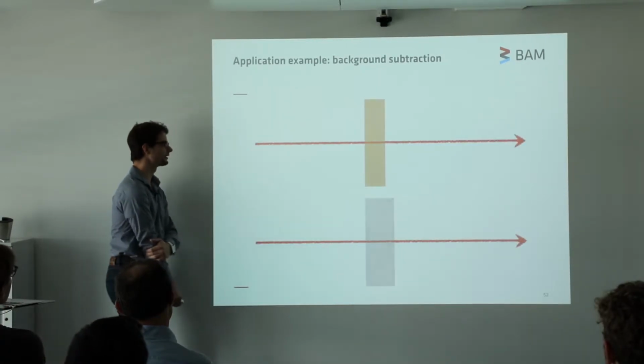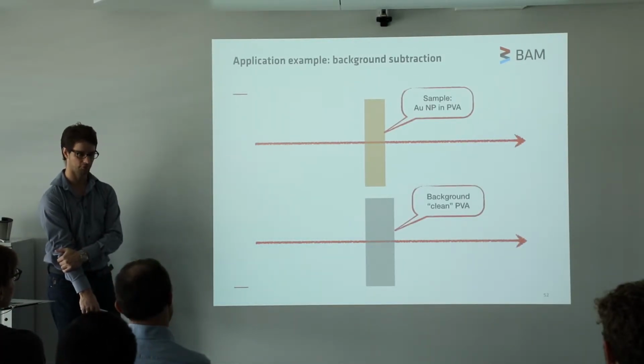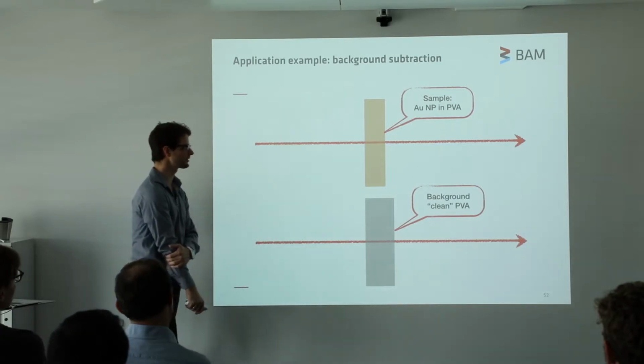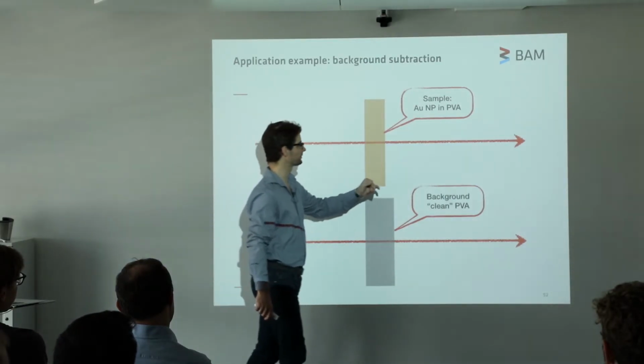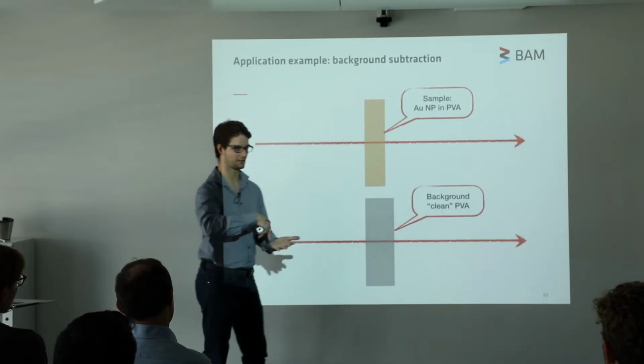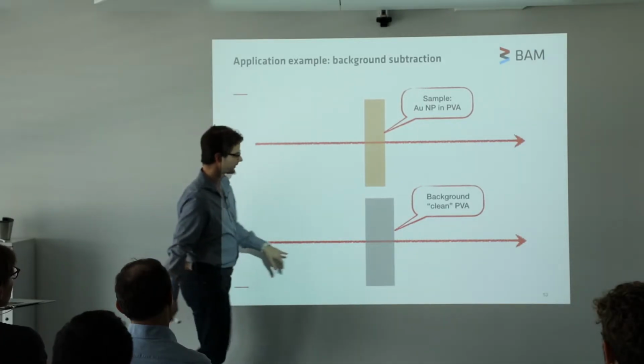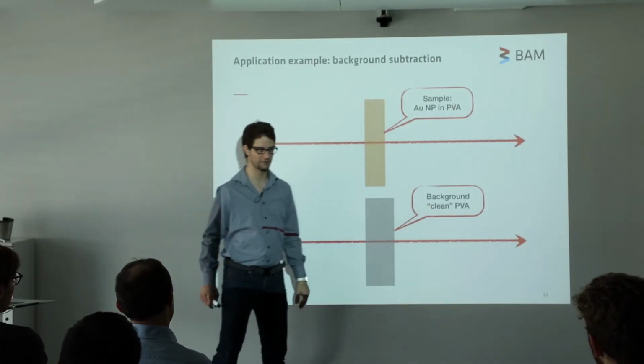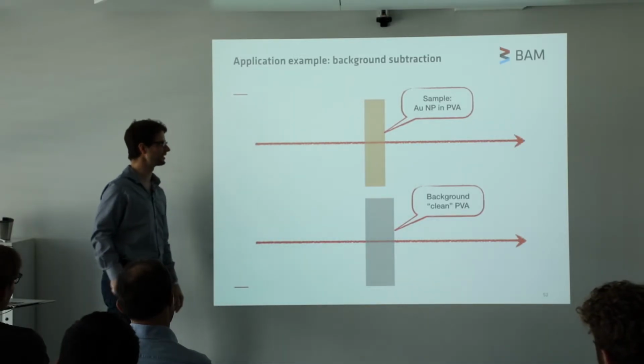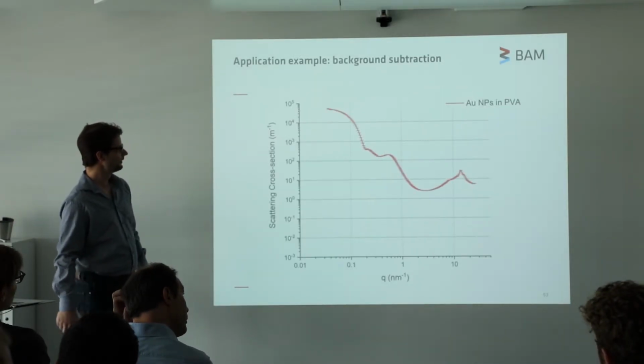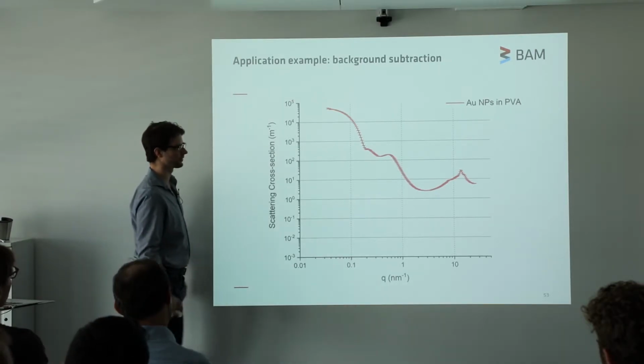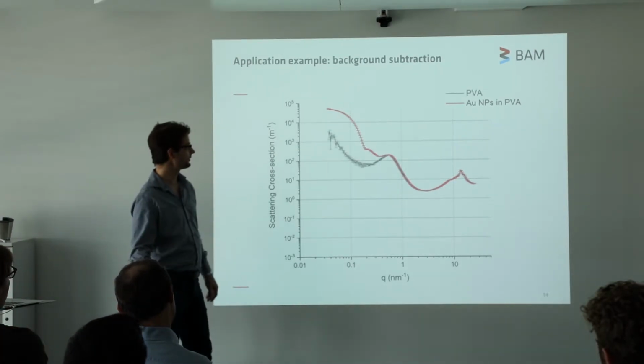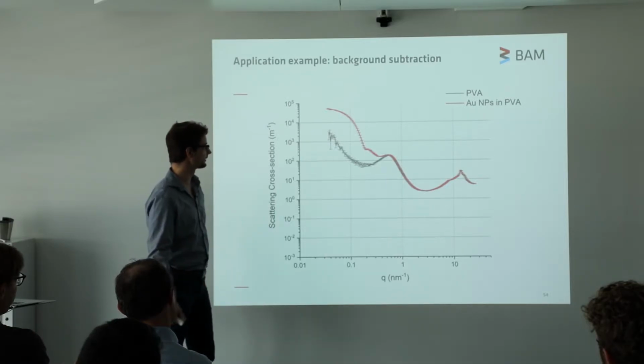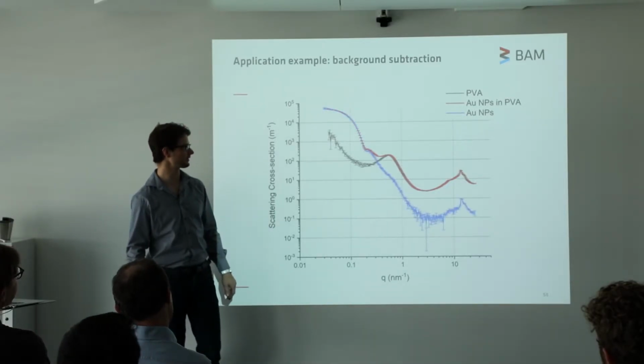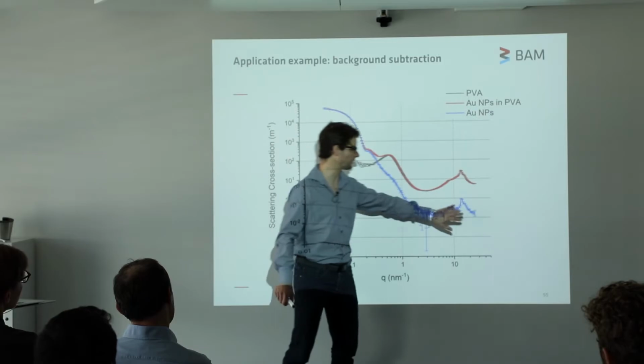One example is that of a background subtraction. These are samples from Vittorio Saggiomo from Wageningen University. He has gold nanoparticles embedded in PVA, which he can then 3D print. Of course, from that, we need to subtract a background of clean PVA, and these are not the same thickness. So this is the data from the gold nanoparticles in PVA. This is the PVA itself, and then we can subtract the two from one another. You see, it works pretty well.